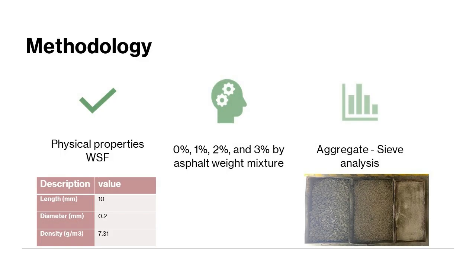This fiber is put into hot aggregate at different rates of 0%, 1%, 2% and 3% by weight of asphalt mixture. The research aggregates were analyzed using sieve analysis to ensure they meet the Superpave standard gradation requirements. The test procedure involved drying the aggregate sample in an oven at 100 Celsius for 24 hours before sieving.